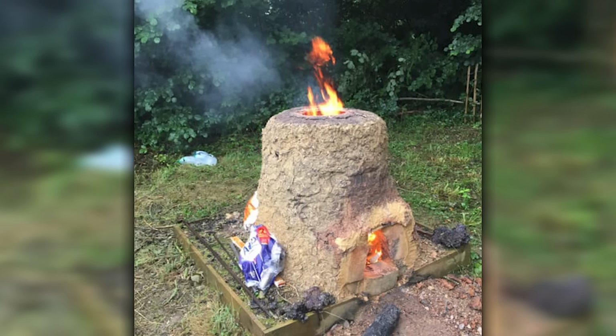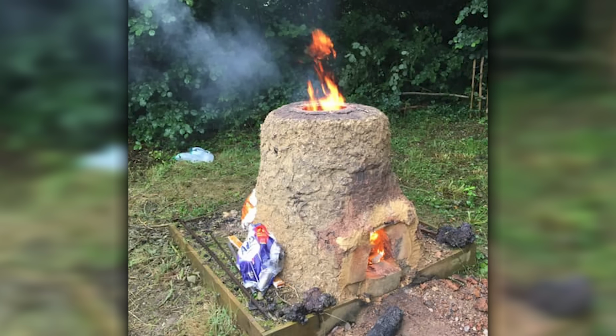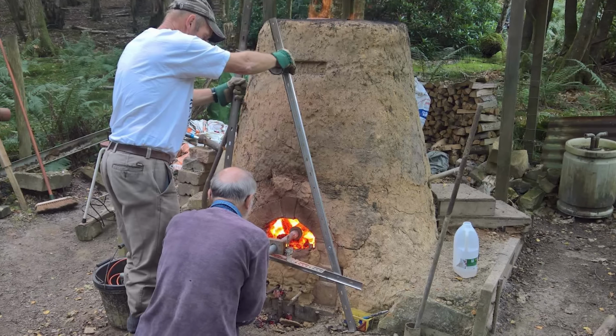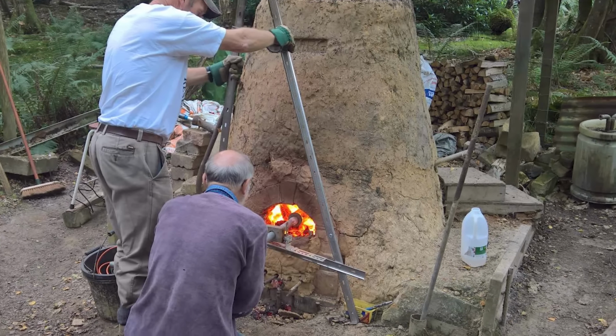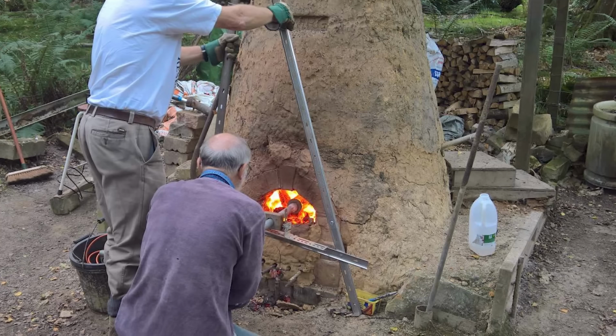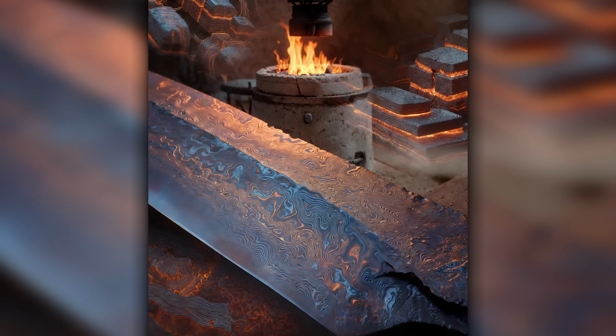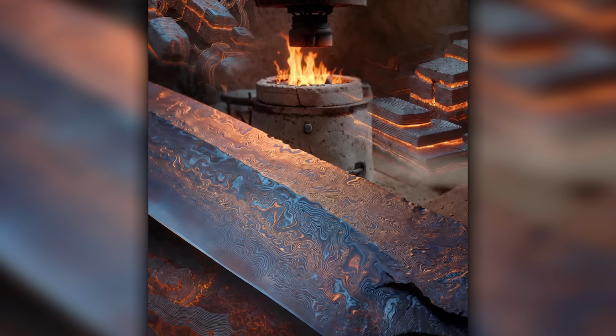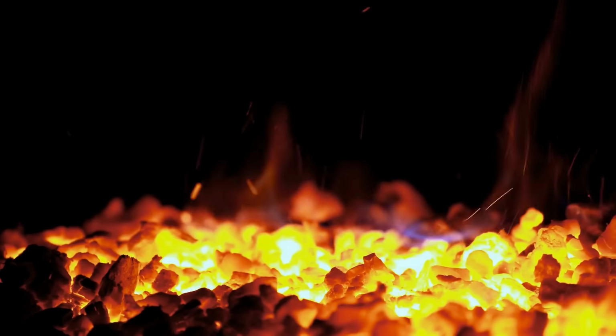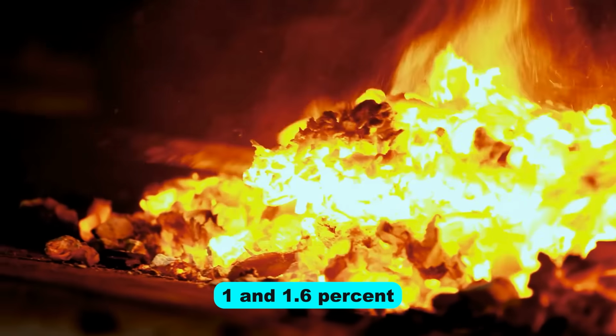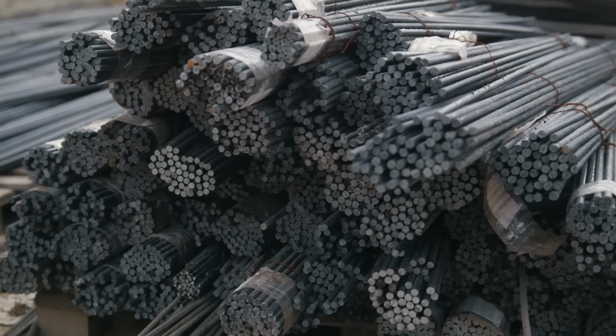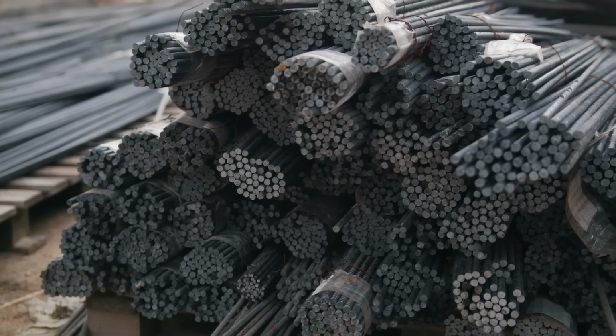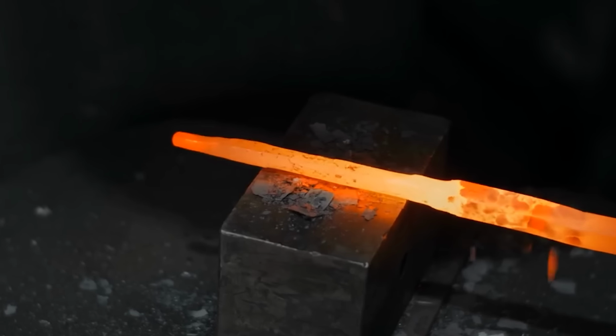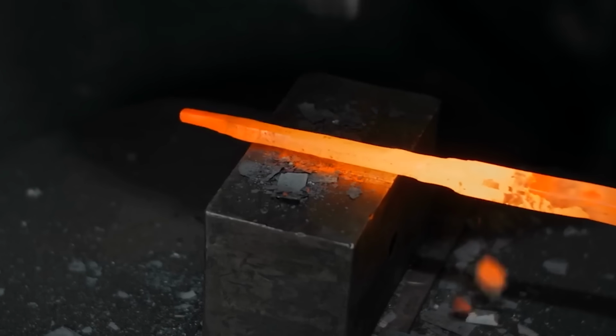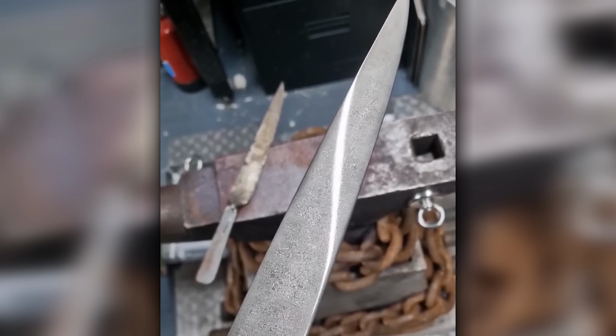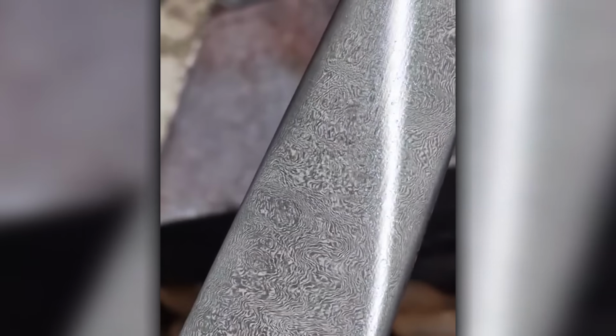The crucible was removed and allowed to cool slowly, over several days. That slow cooling allowed the carbon to segregate into distinct zones within the crystal structure, rather than distributing evenly. And this segregation was the foundation of everything that made Wootz special. The final carbon content is between 1 and 1.6%. Modern metallurgists call this ultra-high carbon steel. At that carbon level, the steel should be hopelessly brittle. But Wootz blades were famously flexible, and nobody could explain why.